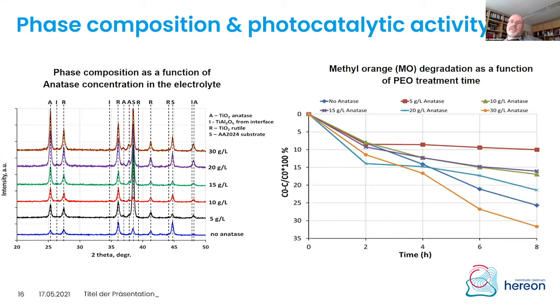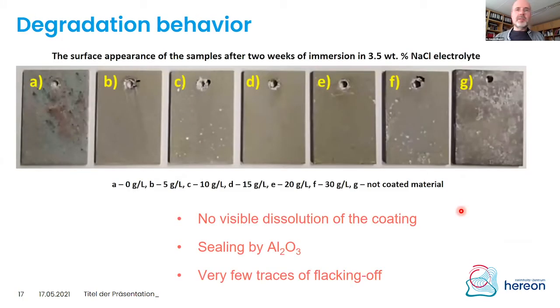But we see also that there's a clear trend that from the beginning, when we have 5 grams to 10, 15, the activity is increasing, but for some reason without anatase addition, we still have reasonably good properties for our coating. So the conference is about corrosion and degradation. So I would at least at the end also talk a little bit about the degradation of those coatings.